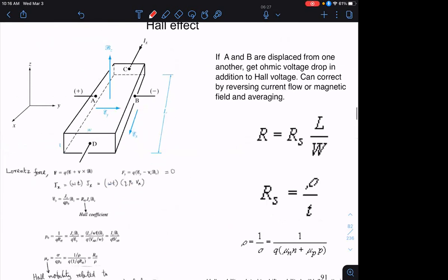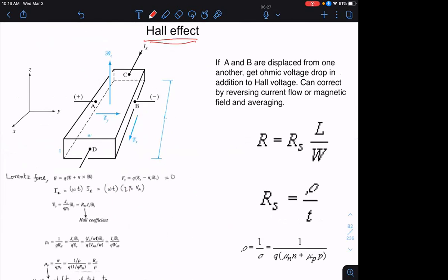Now, I was hoping to finish up the Hall effect. I'm not going to test you on that in the exam, but I think one of the homework problems that are due involves the Hall effect. I'll discuss this on Monday, but to solve the problems, hopefully you can read ahead a little bit. It has to do with the fact that in a semiconductor, you can apply both an electric field and a magnetic field. And if you have electric and magnetic fields, you may remember from physics, electrons are subject to what's called the Lorentz force, E plus V cross B. Because of this, if you drive a current in this direction and have a perpendicular magnetic field, you develop a voltage in the transverse direction, the so-called Hall voltage. And from that measurement and the measurement of the resistance, you can infer what the mobility and the carrier concentration in a semiconductor are. I'll discuss this in class on Monday. This will not be in the exam, but I think you'll need this in one of the homework problems. Okay, my apologies, I couldn't get to this.